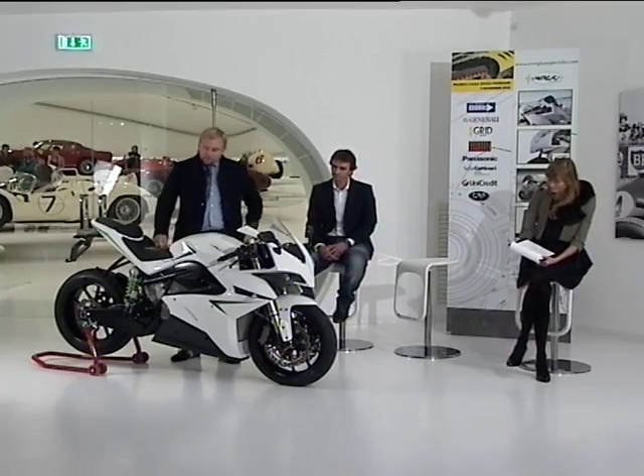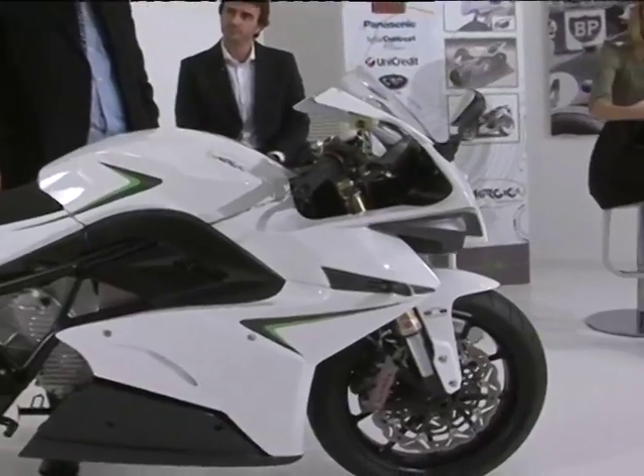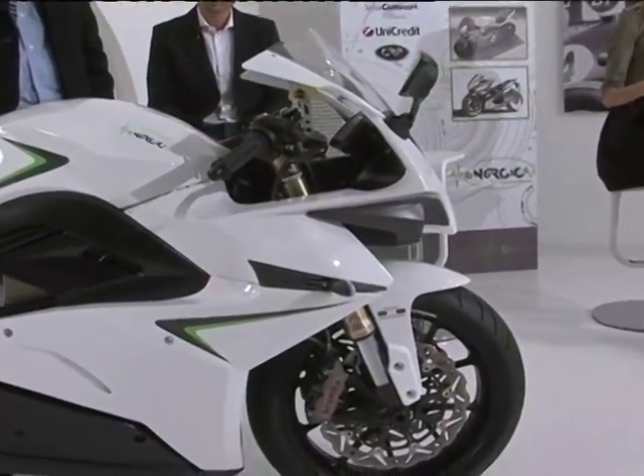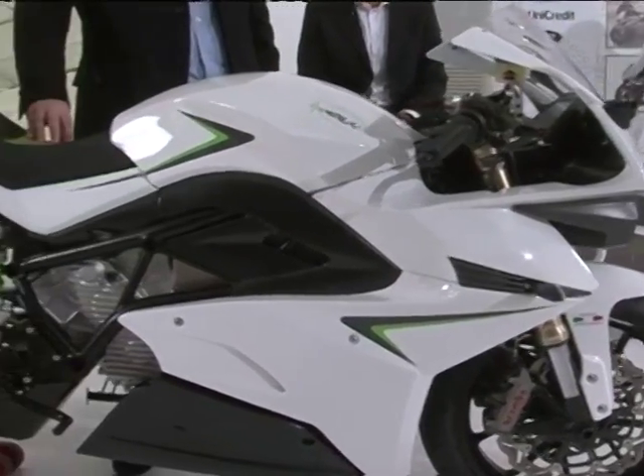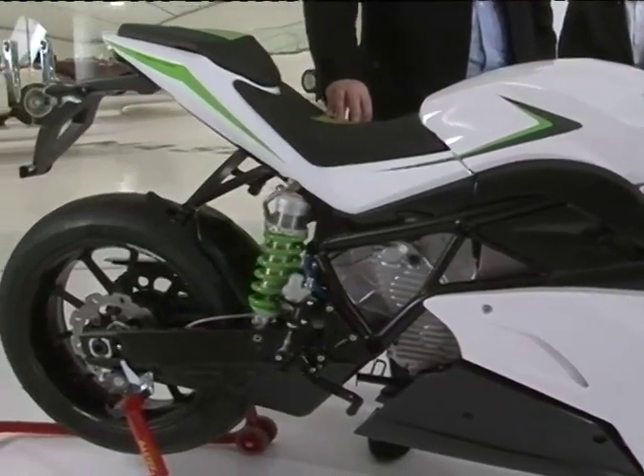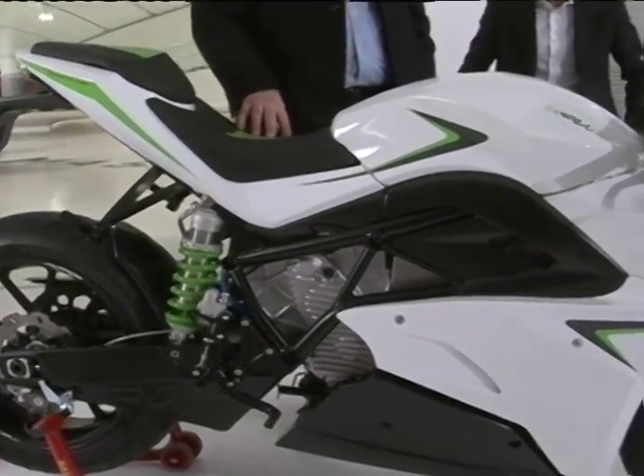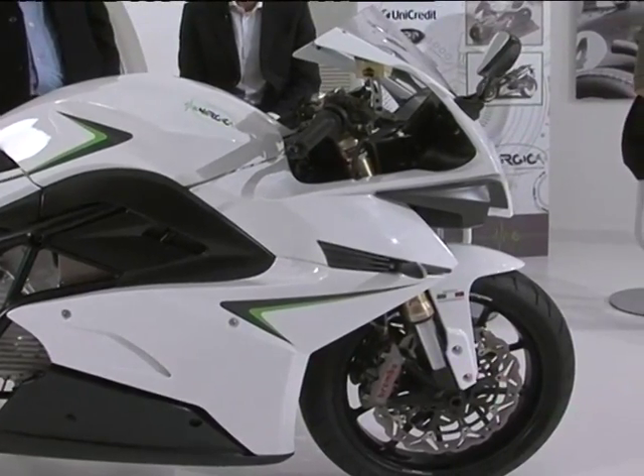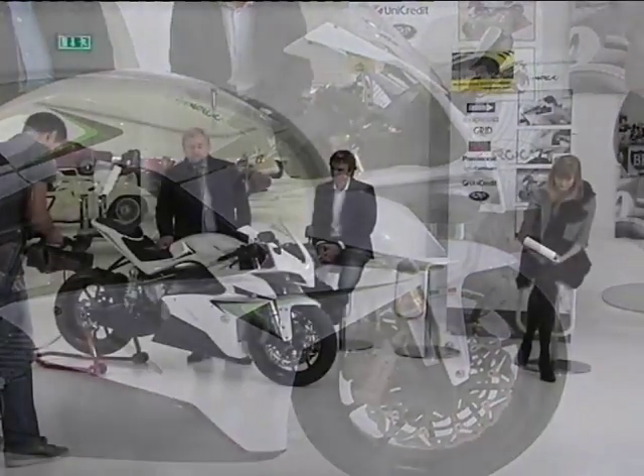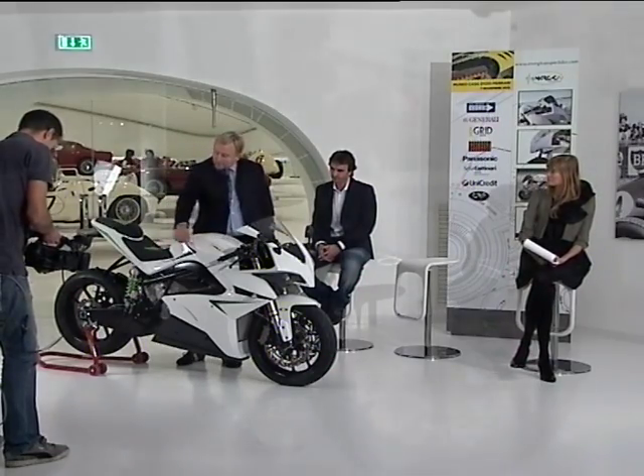Due to the lack of time, we decided to use two technologies that are well known in motorsports and in Formula One especially. And these technologies are 3D printing and CNC machining from solid. About the 3D printing, we use the Windform XT2.0 material that is a high-performing polyamide reinforced with carbon fiber. With this material, we made the whole fairing,